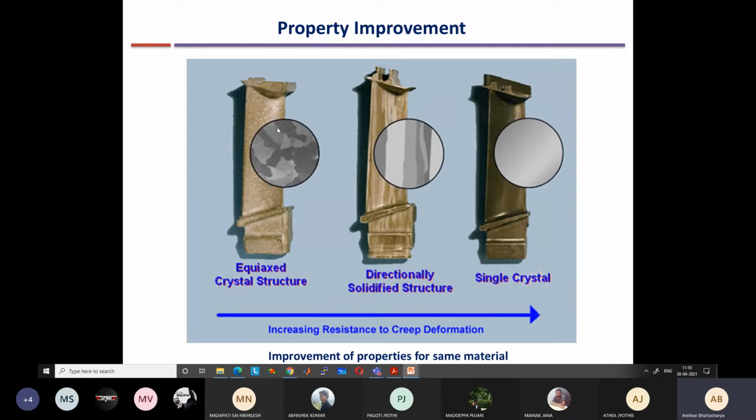So there was a ceramic mold and you poured liquid metal in it, and then it solidified, it formed an equiaxed grain structure, meaning nuclei formed everywhere. So everywhere the cooling was uniform, and it resulted in the formation of a large number of small solid nuclei. Each of the nuclei grew into one solid grain. Ultimately the entire structure was an equiaxed grain structure, with multiple grains together like this.